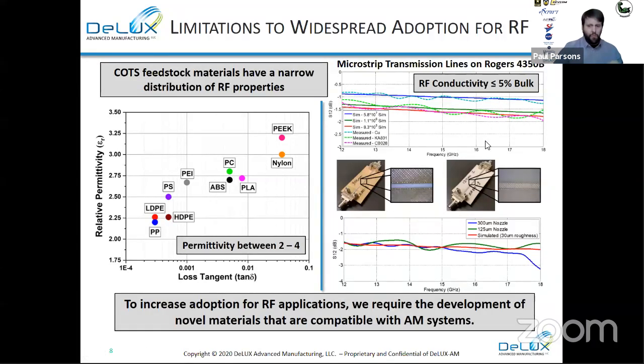On the other hand, and probably the more important materials development process for RF applications, are the conductive materials themselves. We've looked at a lot of the commercially available printable inks and pastes at high frequency on a base Rogers board. And it turns out we are very limited in the RF conductivity, especially as the frequency increases. This can be attributed to the materials not being able to fully cure and sinter on these polymer substrates, because if you set the temperature high enough, the polymer substrates begin to warp, break down, and then decompose altogether. And we want to avoid that.